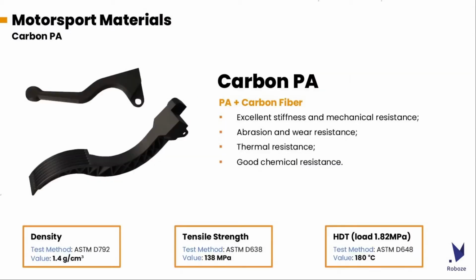Roboze carbon PA is a composite material based on a polyamide 6 matrix reinforced with carbon fiber at 20% in weight. The reinforcement enhances the main properties of nylon, such as resistance to abrasion and wear, providing it with greater thermal and mechanical resistances. For this reason, the filament can work up to 180 degrees Celsius, while from the mechanical point of view, it shows a tensile strength of almost 140 megapascal and an elastic modulus of 15 gigapascal, which is much higher than most other composites available for FFF 3D printing solutions.